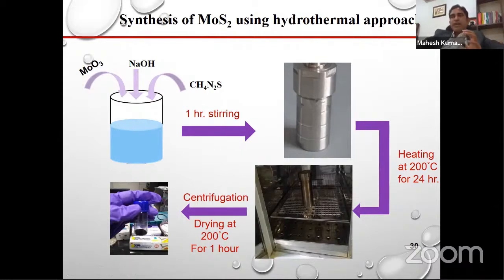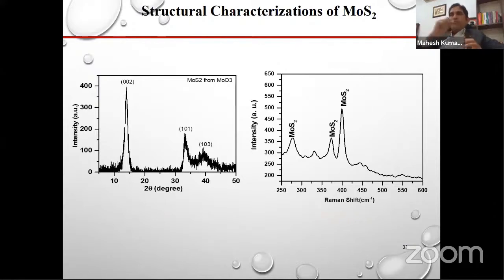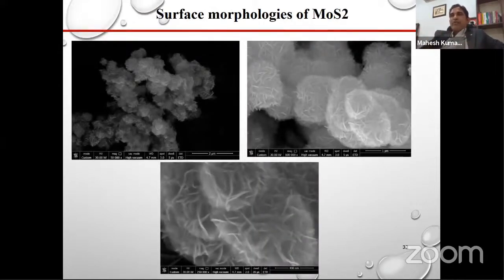This black powder we have characterized, and we found that MoO3 is converted into MoS2, which we confirmed by X-ray diffraction and Raman spectroscopy. Second, we have done electron microscopy, and in sensors, when we are sensing, we need a large surface area. You can see these flakes, because of which we have a large surface area. These monolayers are making flower-like structures.